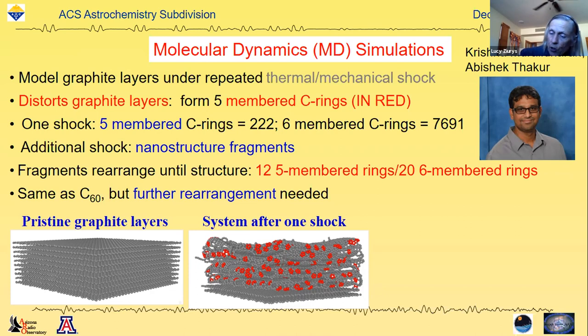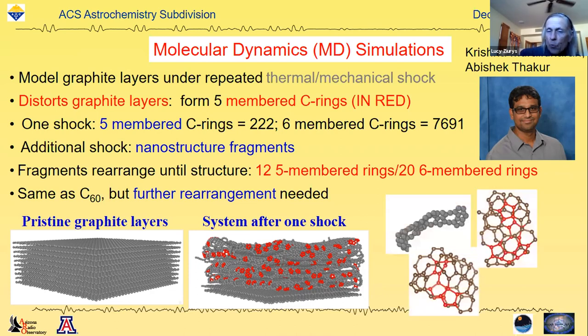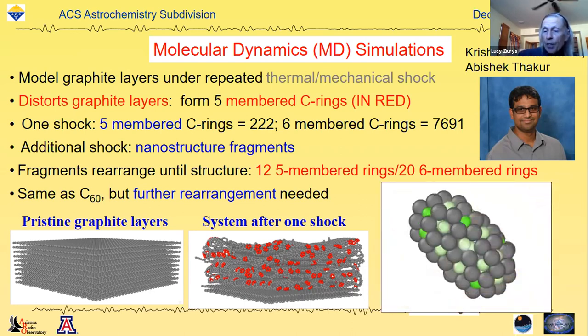And additional shocks done in the simulation begin to really distort the graphite. And you get pieces, graphite fragments, nanostructure fragments coming off the surface of the graphite. Here are some of them there. They contain both 6- and 5-membered rings. And finally, with another shock, you'll actually form a structure that looks like this, which has 12 5-membered rings and 20 6-membered rings, exactly like C60, but it's not quite symmetrical and spherical yet like C60. And that's the next step in the simulation, which we're working on, but we're getting pretty close.